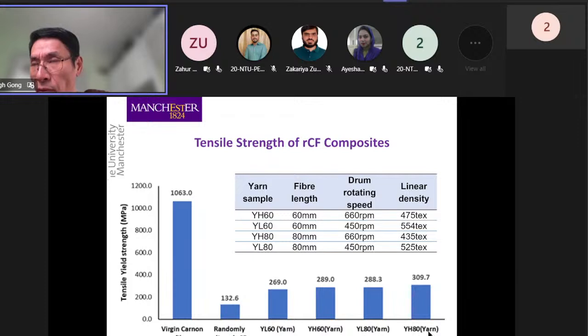What you tend to see is as the fiber becomes longer and when the drum speed becomes higher, the composites tend to get stronger, which is understandable because longer fibers, especially given the poor alignment, will help to improve the yarn strength, because inside the composite, of course, there's interaction between twisting and the resin. I say that because in a normal yarn, the strength of the yarn comes from friction only between the fibers. But in the composite, you have the resin, which is like a glue to hold the fibers. So there are a lot of these different interactions going on.